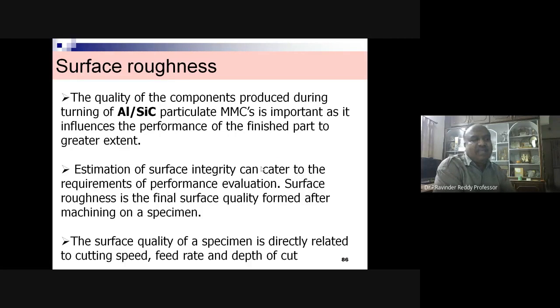After that, we have measured the surface finish, the quality of the components produced during the turning. Aluminum silicon carbide particulate MMC is important, as it influences the performance of the finished part to a greater extent. Estimation of surface integrity can cater to the requirements of performance evaluation. Surface roughness is the final surface quality formed after machining. The surface quality of a specimen is directly related to cutting speed, feed rate, and depth of cut.